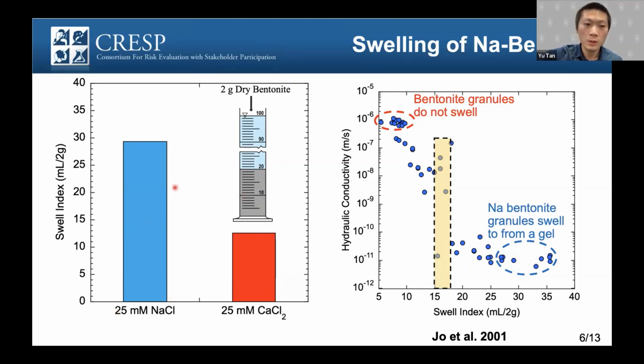In this column, if we use sodium chloride in the solution and run the tests with sodium bentonite, it will generate high swelling. A high swell index means high swelling, and it will yield very low hydraulic conductivity, 10⁻¹¹. But if we test the same bentonite with calcium chloride solution, it will develop a low swell index and yield high hydraulic conductivity. So it becomes permeable. It's not able to contain the leachate.